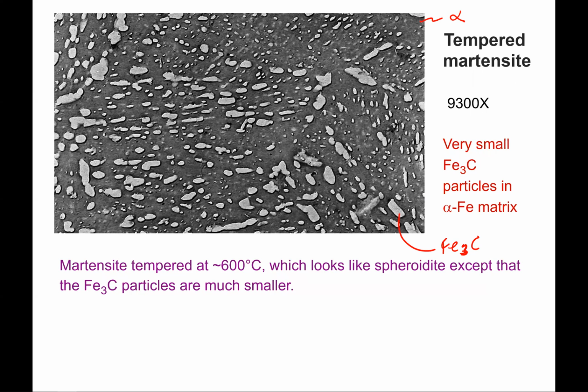Okay, so this brings back a lot of ductility to this material, but these cementite particles are extremely fine, and so they resist the movement of dislocations through this structure because there's so many particles, there's so many impediments to trying to move dislocations throughout. And you can see all of the different length scales that are in this ferrite structure.